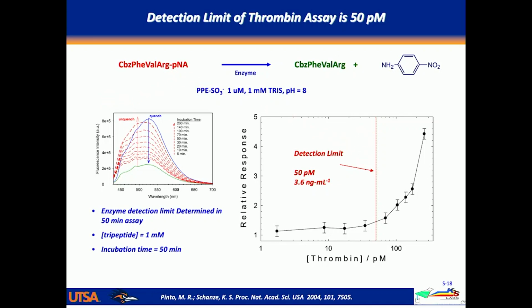And doing experiments where we measured the detection limit, it turns out we were able to measure the enzyme down at about 50 picomolar concentration, again, using about a 1 hour incubation time. So we basically mix the system together and then read out the fluorescence after an hour of incubation.